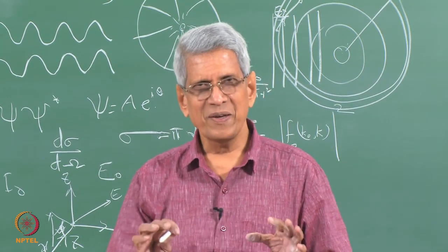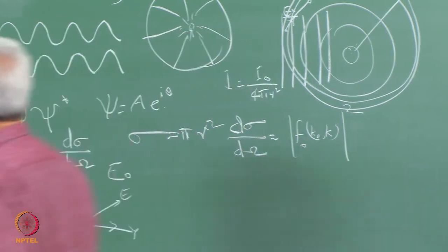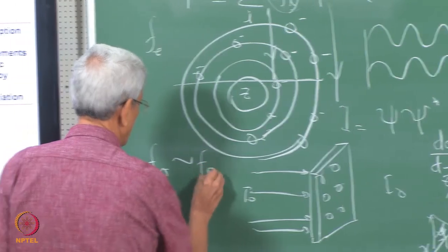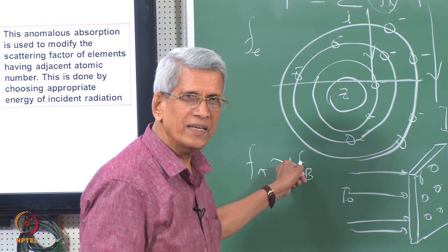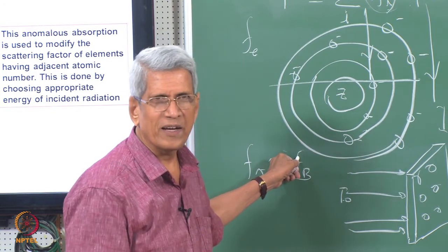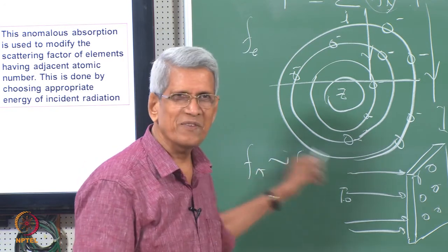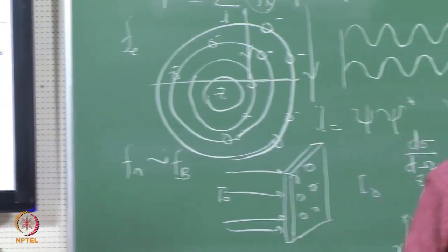That means that the superlattice reflection intensity, which we write as Fa minus Fb, if A and B values are close by, almost turns out to be 0, like that of a disordered material. We could not see that order is there. By artificially changing these values, we can still find out information about ordering.